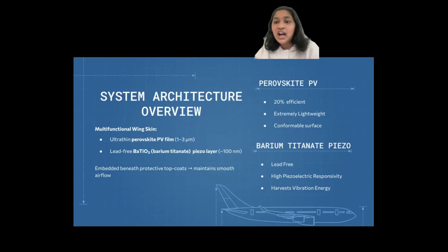The second is a 100 nanometer barium titanate piezoelectric nanostructure layer, tuned to respond to vibration frequencies around 120 Hz, which is typical for cruise level aeroelastic oscillations. And instead of mounting anything on top of the wing, these layers are built into it. So the wing doesn't just retain its structural and aerodynamic properties, it becomes an active generator. Together, the PV and piezo layers form a multifunctional skin capable of harvesting solar energy and converting vibrational energy into electrical output, all while preserving aerodynamic performance.